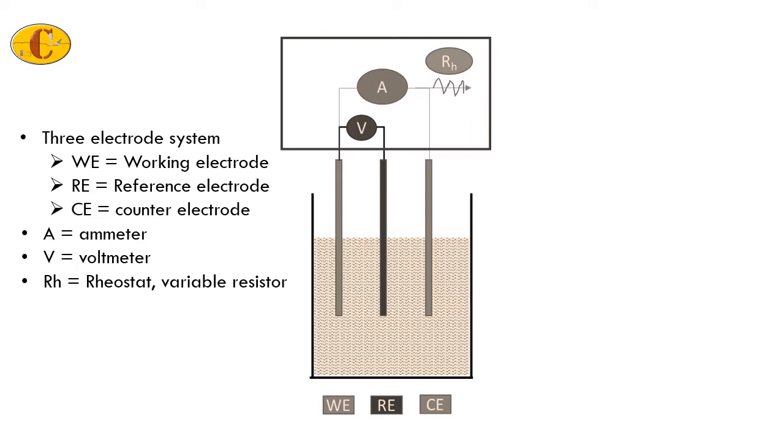For example, if we connect the working electrode with copper, the copper may affect its behavior depending on the galvanic coupling between the two. Hence, we don't want that kind of galvanic coupling, which is why we need a reference electrode.